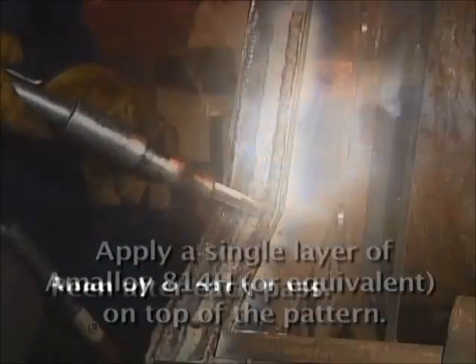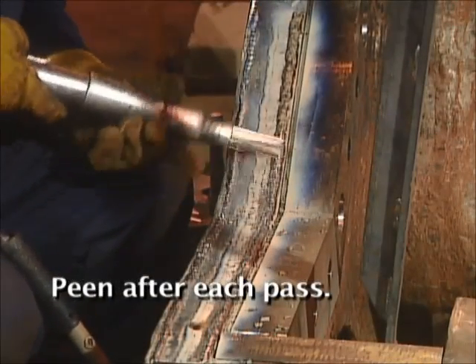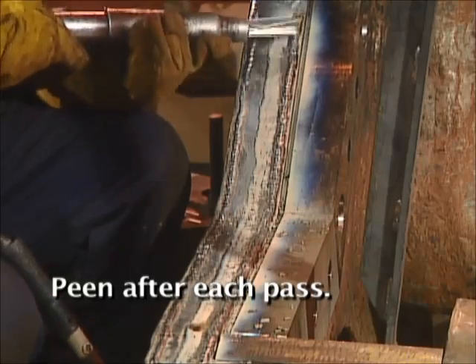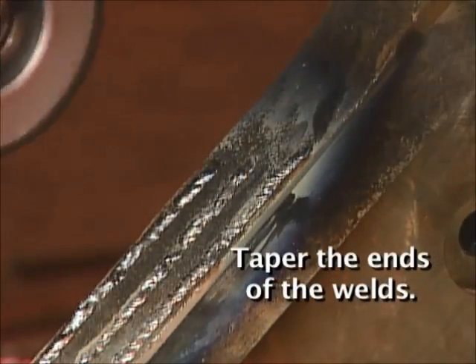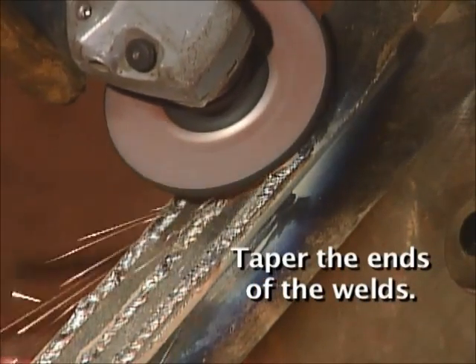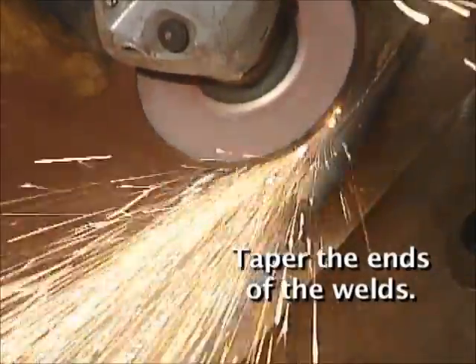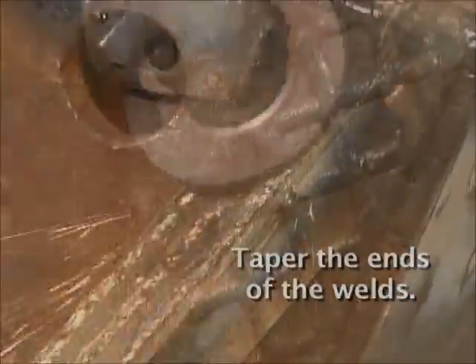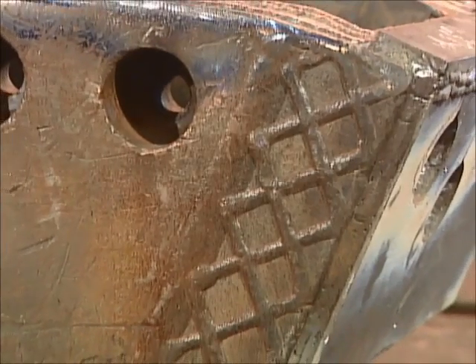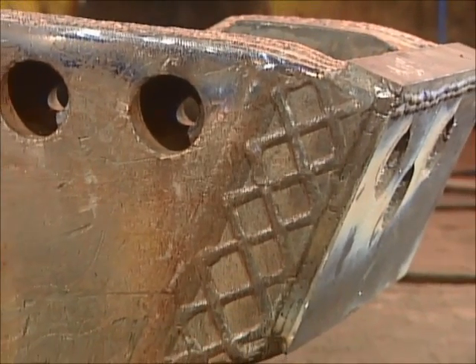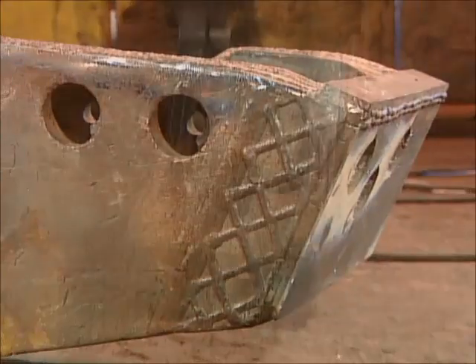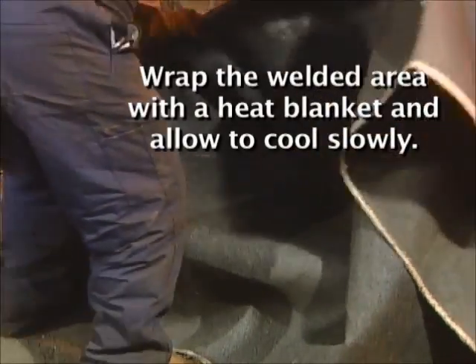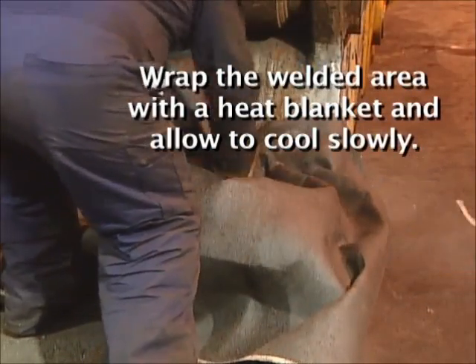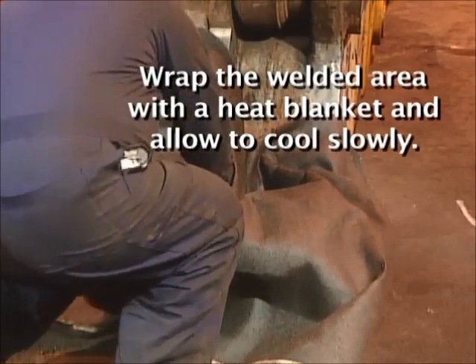Apply a bead of Amalloy 814H or equivalent hard surface rod on top of each of the underlayment beads. It is important to use an air-operated slag peener on each pass of weld to relieve stress. When all the beads have been covered, use a grinder to taper the end of each weld down to the base metal, but be careful not to undercut the welds. Using proper welding technique, the sides of the crossplate should be hard surfaced with a diamond or crosshatch pattern. When welding is complete, wrap the weld areas with a heat blanket and allow to cool slowly to ambient temperature before returning the shear to service.